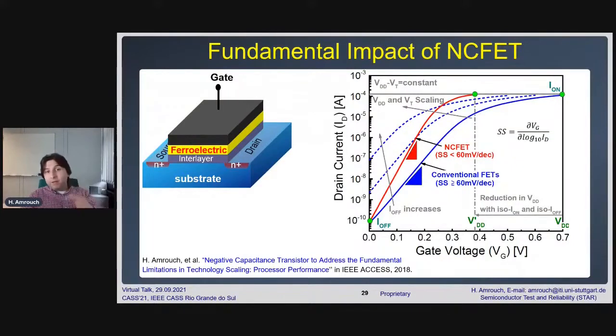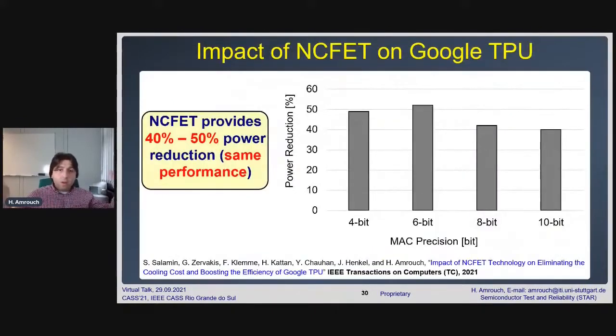We see here in the red curve, which is the NC FET, how it's steeper and could achieve the same baseline on current at much lower voltage without any increase in the leakage, without any increase in the off current. That means we can operate our circuits at much lower voltage without any loss in the performance. What does that really mean for the neural processing unit? Well, we have recently answered that question, and we did the analysis using the complex framework that I have shown you, and it was using the Google TPU example.